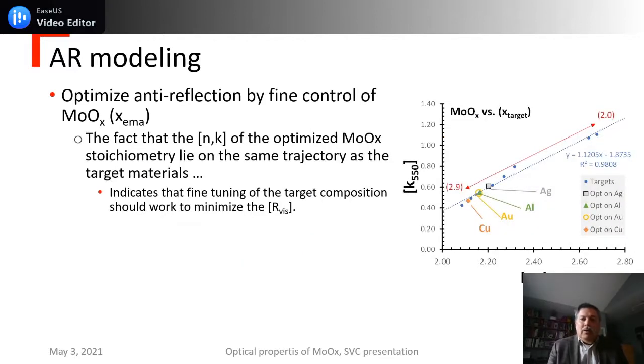Well, those stoichiometries that we have discovered, I promised that we would look at the trajectory. All of those stoichiometries that we have optimized by using the Bruggeman effective medium approximation all fit on this line. And that's quite encouraging, because it tells me that we will have the chance of making a target of the optimized stoichiometry to produce these films.